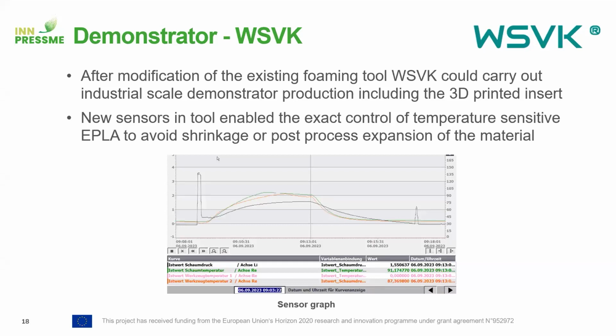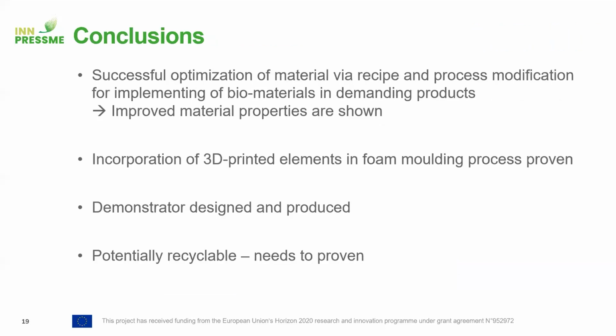As a preliminary conclusion, it can be said that the modification of the foaming tool at WSVK enabled the production of the demonstrator, and also installation of new sensors in their tool enabled the control of the process with regards to that very temperature sensitive material PLA, which was used in this case. And as a final conclusion, we can say that we successfully optimized the material with regards to mechanical and thermal properties, so that we could produce such a demonstrator.